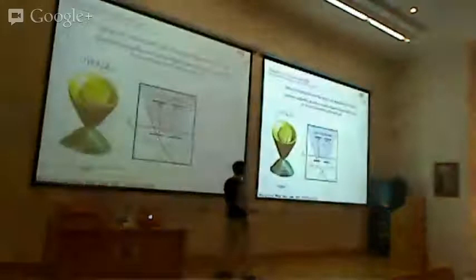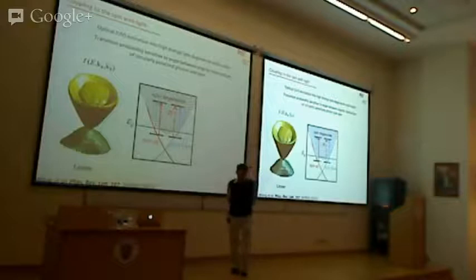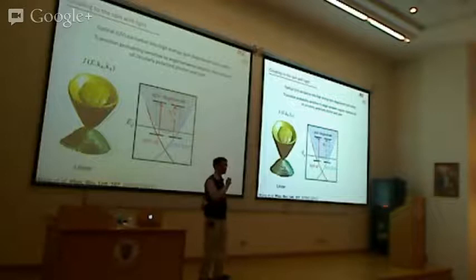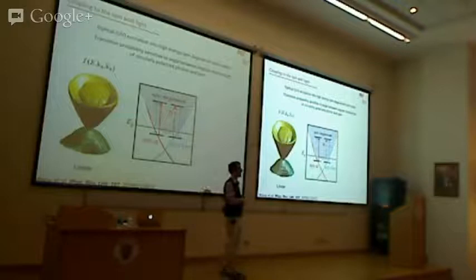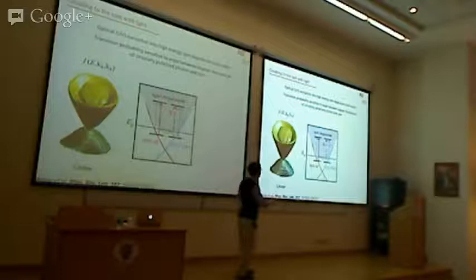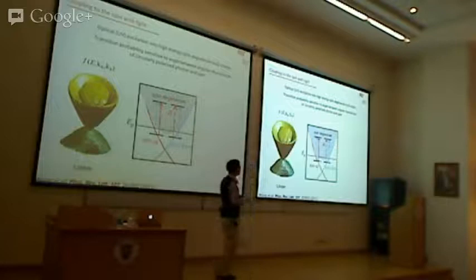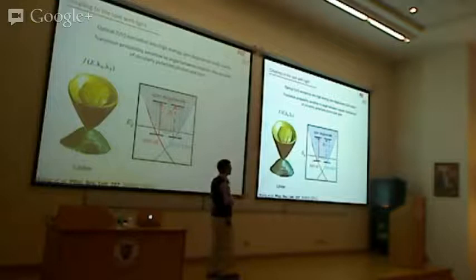The next question is how to measure spin. We don't want to do the Mott detector approach because it's very time-consuming. Instead, we used circularly polarized light. We used the fact that right and left circularly polarized light will couple differently to spin-polarized bands — spin up versus spin down — with different matrix elements. So perhaps you can use the difference between right and left circular polarization to figure out the in-plane spin polarization. We shot right and left circularly polarized light and took the difference.